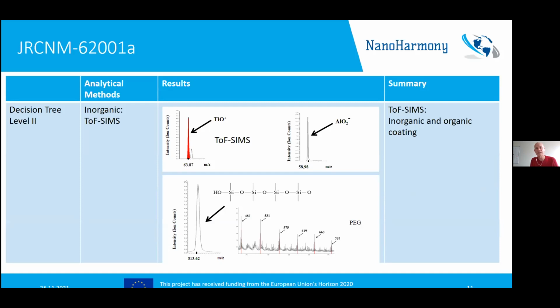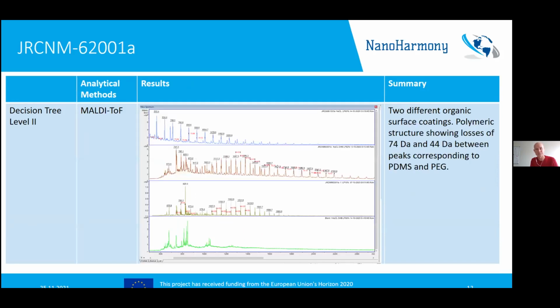So it is a general outcome of this intra-laboratory experiment that you have to have quite many different analytical techniques in order to analyze a broad range of nanomaterials and their surface chemistry. This is, again, for titanium dioxide, MALDI-TOF, showing characteristic peak patterns of the different organic polymers. You can see how the separation between the peaks reveals the monomer or part of the monomer structure in the polymer.